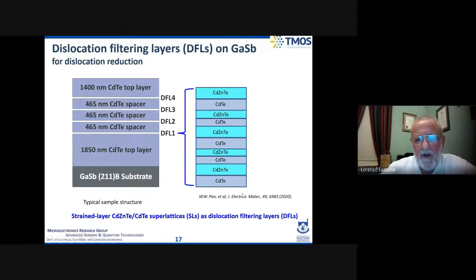We have worked on, and other people are working on, such technologies when you're growing mercury cadmium telluride or any semiconductor on a lattice mismatched substrate. We've used in our MBE system what we call dislocation filtering layers, which are very thin layers with alternating layers of, in our case, cad telluride, cad zinc telluride, cad telluride, etc., multiple layers alternating compressive and tensile stress.